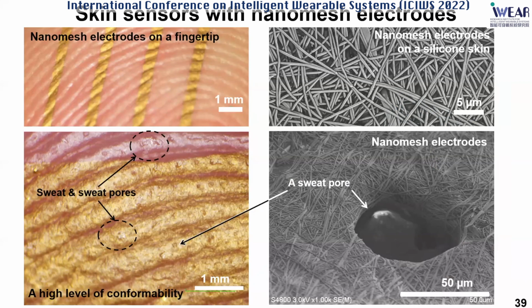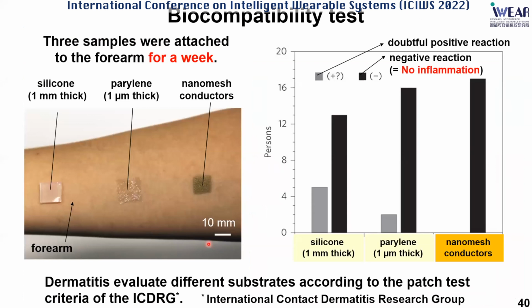And the shining part is the gold. It looks like a thin film gold, a continuous film, but obviously, when we look at the SEM, it exhibits a porous structure. And this is the magnified image. If we look at the dark spots, those are the sweat pores. And we should look at the gold region or non-covered region carefully. The same amount of sweat is penetrating from the sweat pore because of the porous structure. Such natural penetration or vaporization of sweat was critically important to ensure biocompatibility.